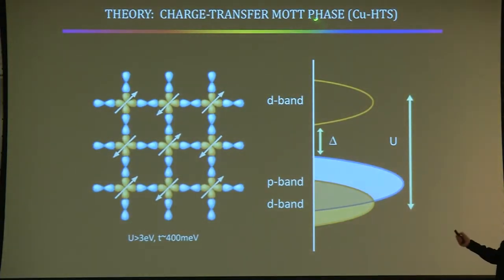So first of all, here's the Mott phase of the cuprates. I'm not going to say anything about its orbital selectivity. If you just focus on the copper atoms, it's very simple. The dx squared minus y squared lower Hubbard band is down here. The upper Hubbard band is up here, and they're split by a large voltage. It's believed but not known for certain to be somewhere around 7 or 8 volts. It's a very large voltage.